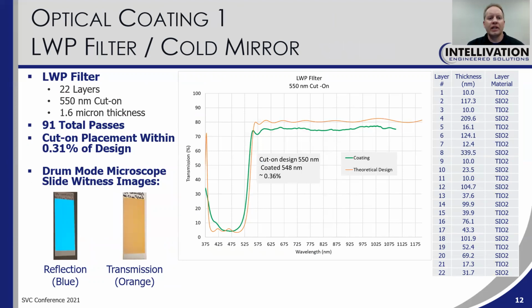So the first coating we're looking at is a long wave pass filter or a cold mirror. And so the recipe is shown over on the right-hand side of this slide, and you can see the 22 layers alternating TiO2 and SiO2, and you can see the thickness of each layer there. And so we designed this coating with a 550 nanometer cut on, and it has a total thickness of 1.6 micron. We used 91 passes for this particular coating. The cut on placement came in within 0.31% of the design.